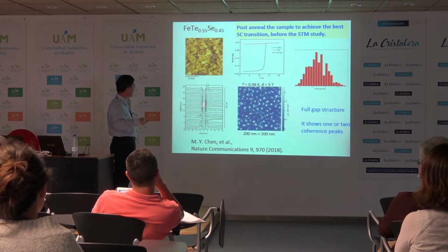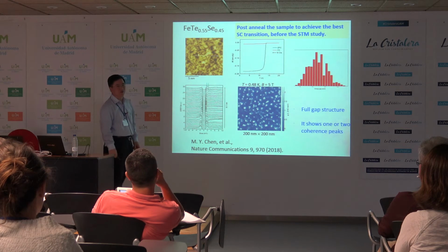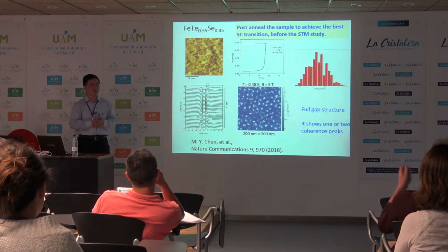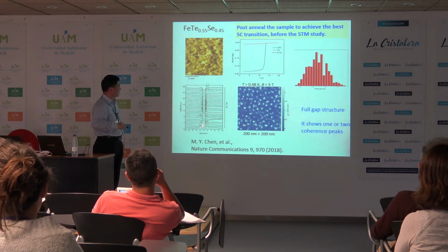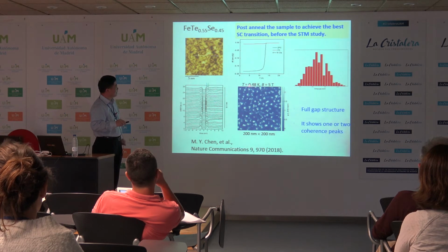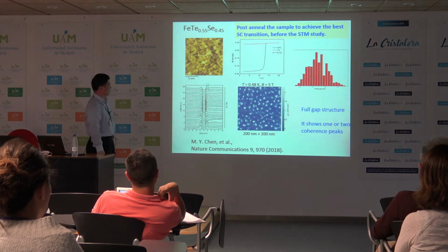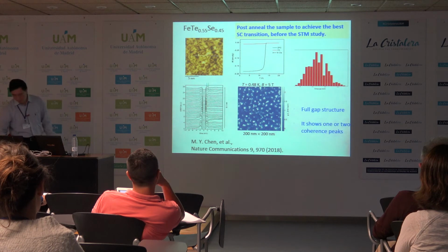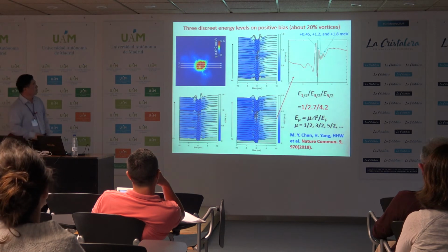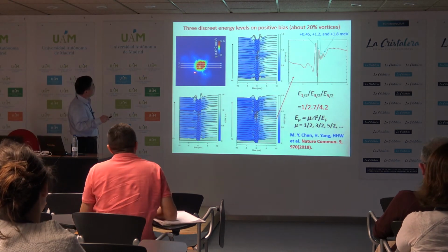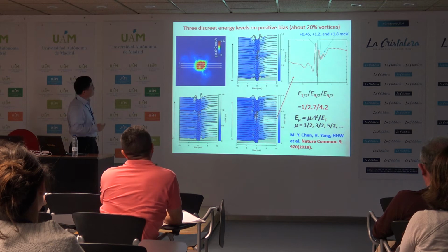This is the spatial tunneling spectrum. In iron-based superconductors, I must say that the coherence peak region is not uniform if you go spatially, but the bottom is quite uniform. It's a full gap. At a field of 5 Tesla and a temperature of 0.48 Kelvin, you can see these dots, which are the vortices. Then we move our tip to measure the tunneling spectrum on vortices. For example, we select one vortex, this is the image of the vortex, and we scan our tip across it.